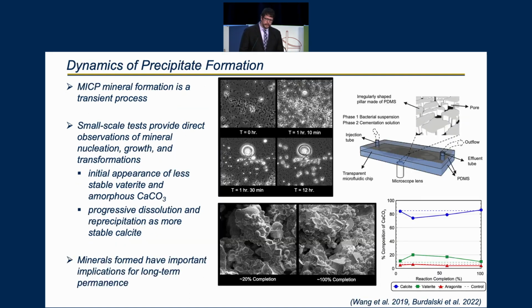Although MICP is commonly referred to as generating calcite, mineral formation during MICP is a transient process with mineralogical changes occurring throughout the treatment process. Small-scale tests, such as the one shown here, have involved microfluidic chips in batch experiments and provide direct observations and monitoring of mineral nucleation, growth, and transformations in time, which clearly show progressions in mineralogy.